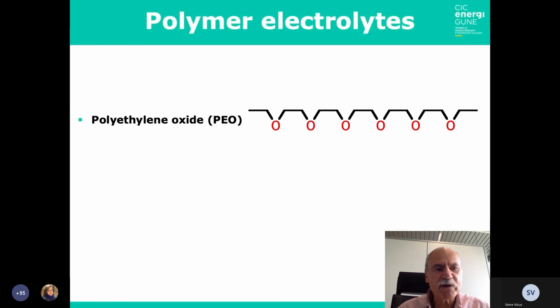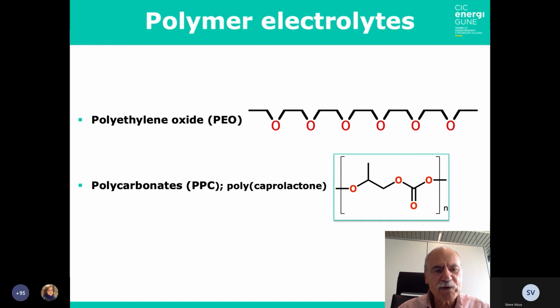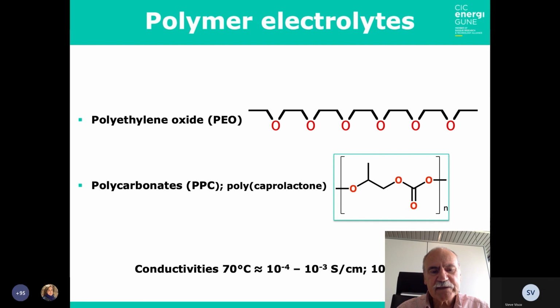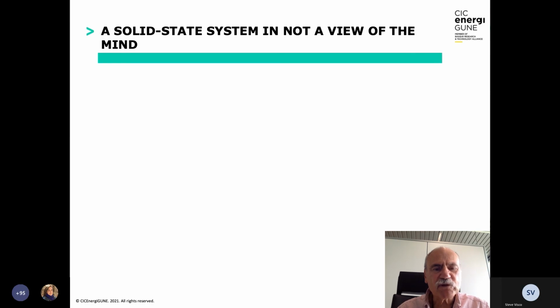Polymer electrolytes, on the other hand, have their archetype with polyethylene oxide, which is highly solvating, or you have polycarbonates, polypropylene carbonate, or polycaprolactone, which is a polyester. And these compounds have got conductivities 10 to minus 4, 10 to minus 3, only when reaching above 70 degrees to activate the motion of the polymer chain. And the conductivity at room temperature is closer to 10 to minus 5, 10 to minus 6, so not usable for practical operation.